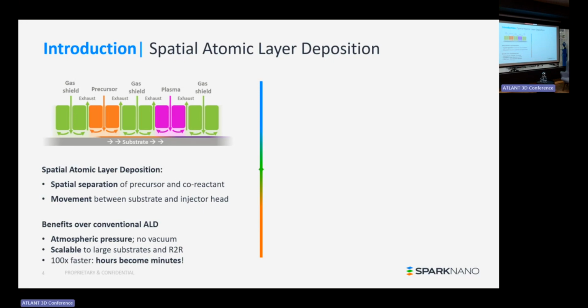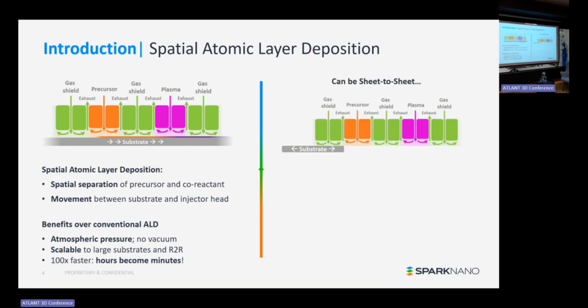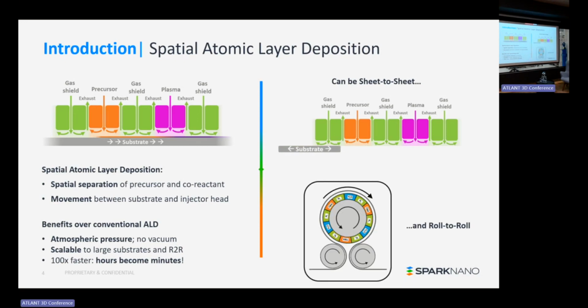We do this at atmospheric pressure, meaning no vacuum. Of course, it's an inert atmosphere, but we don't use vacuum pumps. This technique can be scalable to large substrates and roll-to-roll processing. And very importantly, deposition rates can be 100 times faster than conventional ALD. As mentioned, we can do this sheet-to-sheet on a discrete substrate, wafer, glass plate, a piece of polymer, whatever you want. But you can also do this in a roll-to-roll manner.